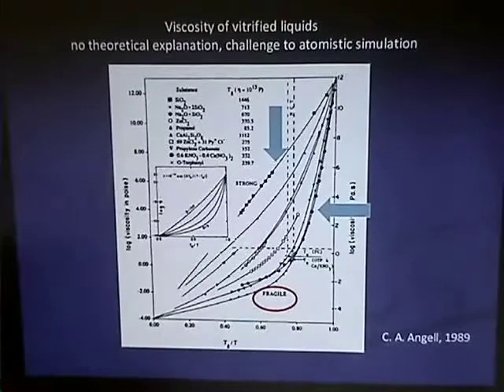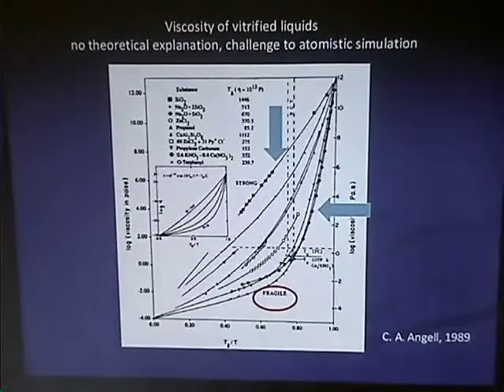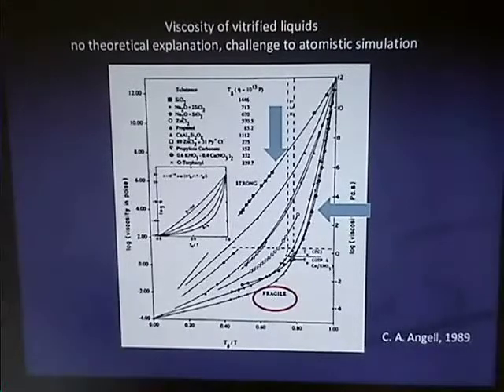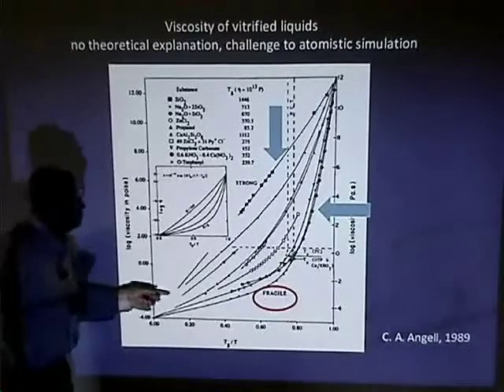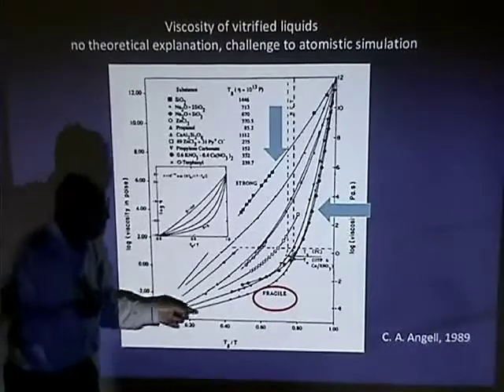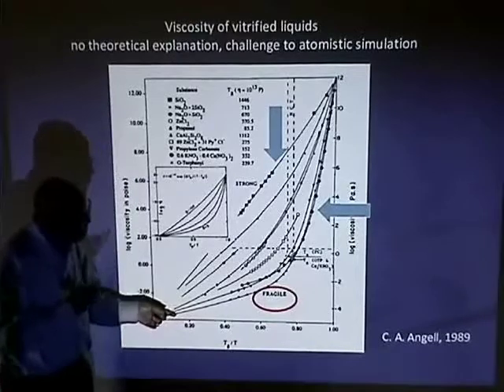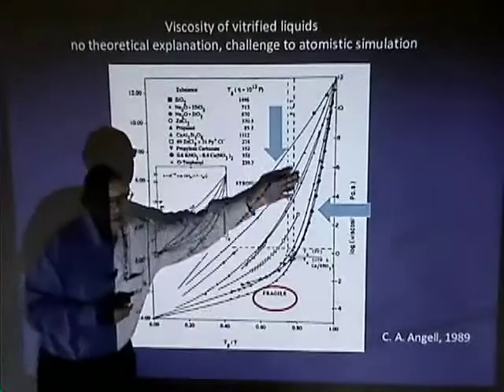And the reason we want to do atomistic calculations is not because we can, but because we can actually uncover some mechanisms of how particles move when the system undergoes some sort of activation. You'd like to know, does it go like a chain-like thing, does it involve bond switching? What do these particles really do? That gives you insight, and insight can lead to further models. But we're stopped here - up to this point, there's no reasonable, credible curve that spans this entire region.